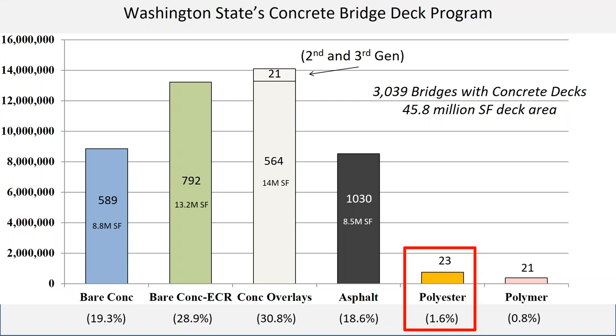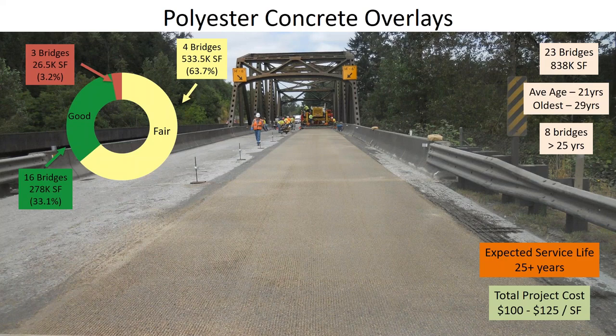So polyester overlays. If we need rapid construction, we will put down a polyester overlay. Here's a bridge on Highway 18. Polyester overlays generally are in fair condition, three of them in poor condition. We have 23 bridges in Washington State on DOT highways with the polyester. Average age about 21 and oldest 29. So we expect about a 25-year life.